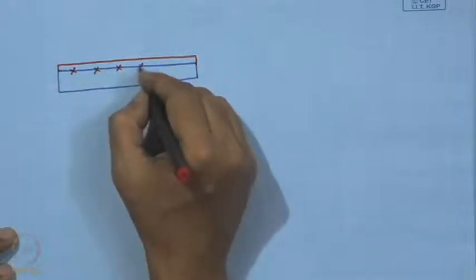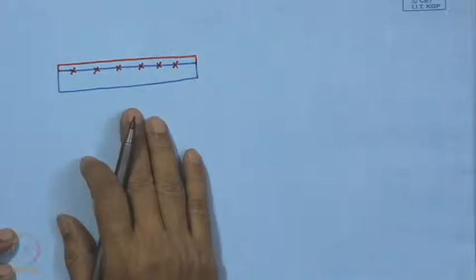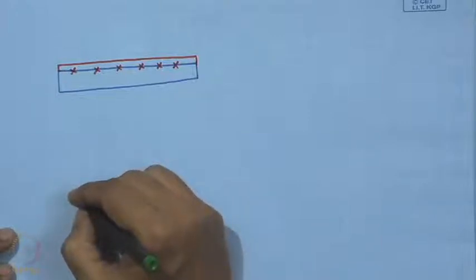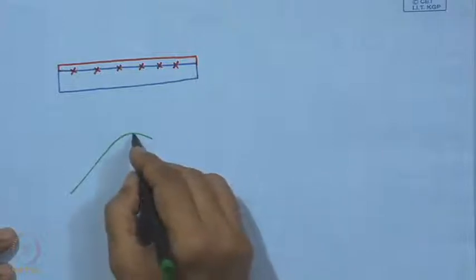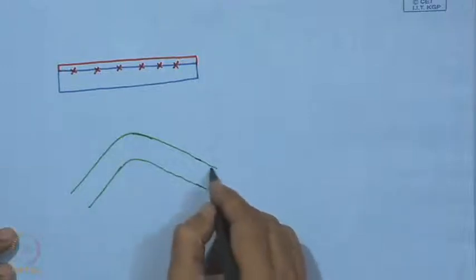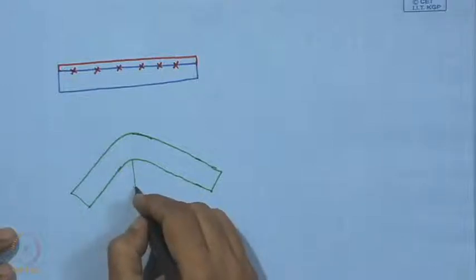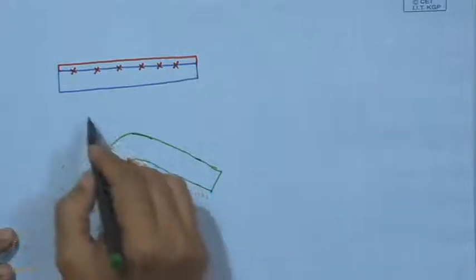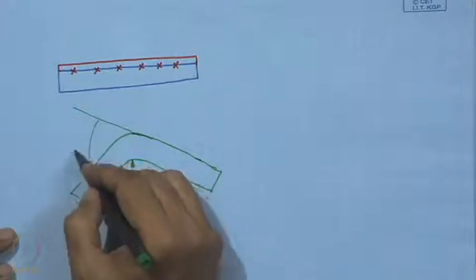Consider a flat substrate with a coating on top — this is the interface. To assess how strong this interface is, we can simply bend the whole piece. During bending, there is a certain radius, and if we extend the reference line, we get an angle theta. Originally theta was zero, and after bending it takes on a certain value.